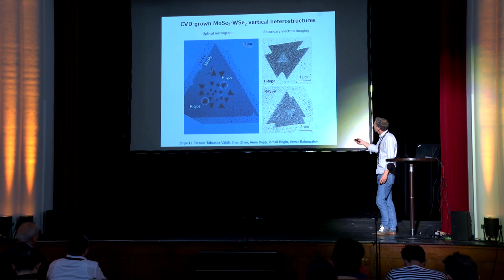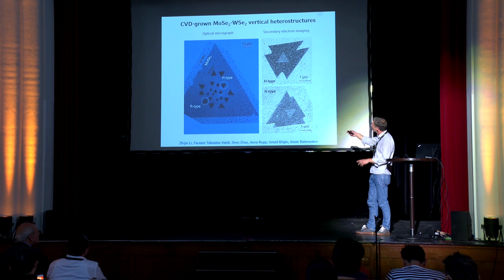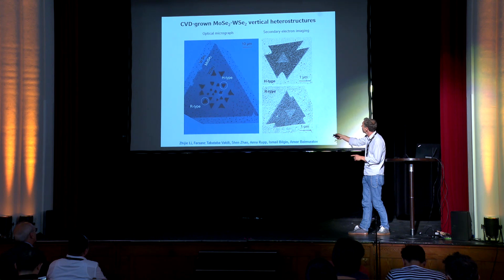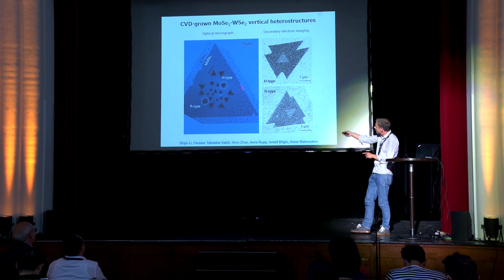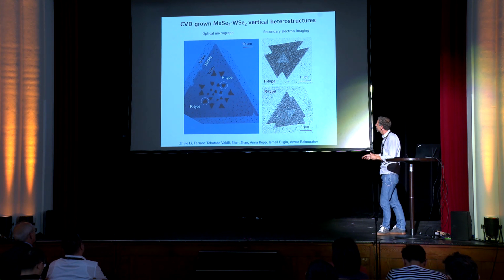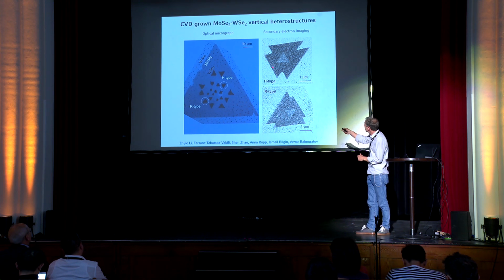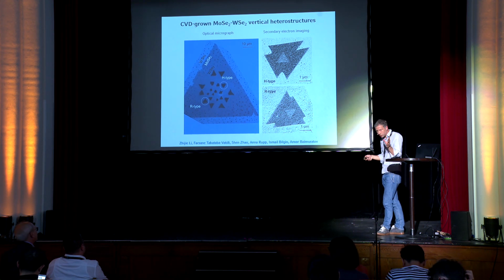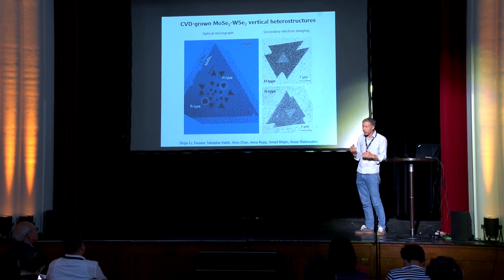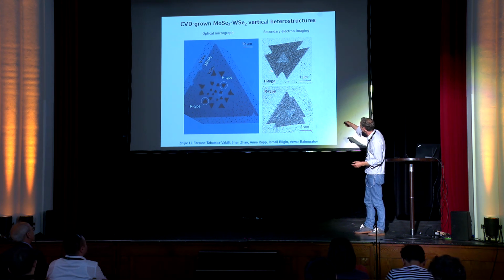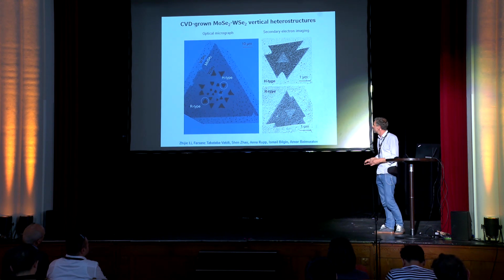And then we see that there is an inner core. So this is a zoom to one of the flakes. The reference now that it's H type is to the edge of a large moly flake. And this is still atomically flat. So this inner core here does not reflect a third layer growing. It's just different in terms of atomic registry from the periphery surrounding it.